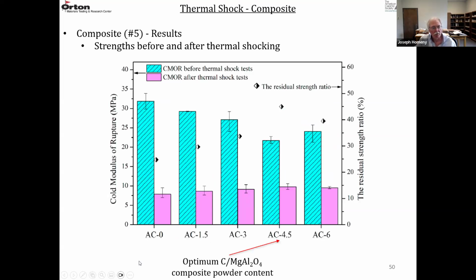And then before and after thermal shocking, these are the bending strengths. So cold MOR, and then residual strength ratios. So this turquoise color is the MOR before shocking, and the purple is after shocking. So AC0, the highest strength, and then as you added more of these carbon spinel powders, the strength started to fall off, and they theorized that the microcracking, when you added this powder, lowered the strength.